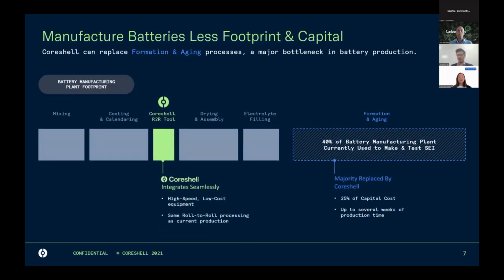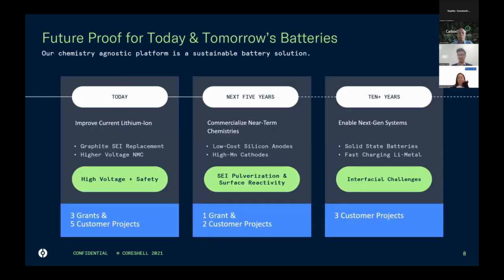Second, as I mentioned, one of the key aspects that I think is a key advantage for Coreshell is that we have something that is scalable to large-scale battery production. We've demonstrated our coatings now in a roll-to-roll tool that we've piloted, which integrates seamlessly into the current roll-to-roll production that's used in high-throughput gigafactories today. And in fact, we can save on the back end of formation and aging processes by replacing a very time-consuming and capital-intensive step on the back end with our upfront low-cost roll-to-roll coating tool. So instead of forming our SEI on the back end, we can coat an artificial SEI in a cheap, fast processing technique.